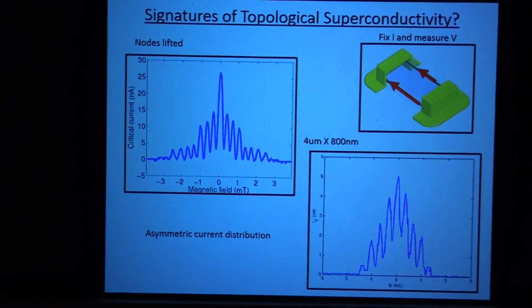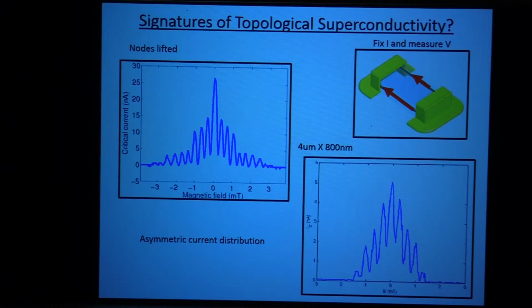Just to point out, right now the physical location of these edge modes is a region that has undergone severe processing: chemical etching, exposed to air, exposed to solvents, exposed to polymers, and so on. So there's a lot of contamination sitting there. It would be lovely if we can find a way to form a junction between a topological quantum well and a non-topological one that sits inside the crystal, that is not formed at the true boundary of the sample. Then I believe that we would have better quantization, less of this unwanted physics playing a role.